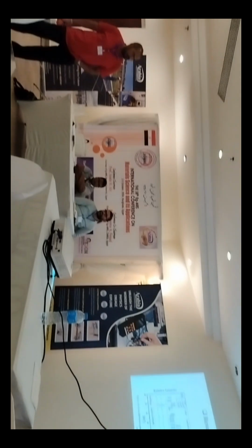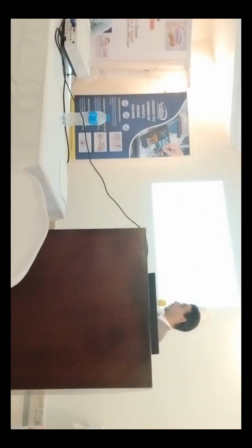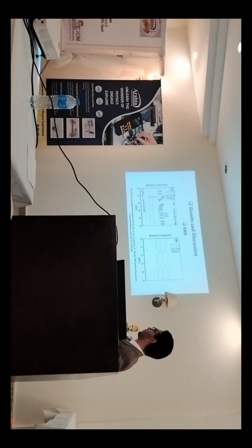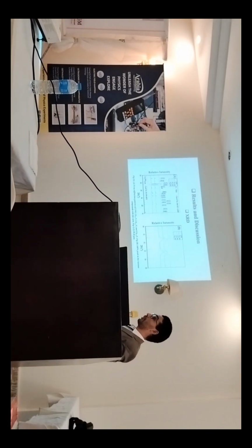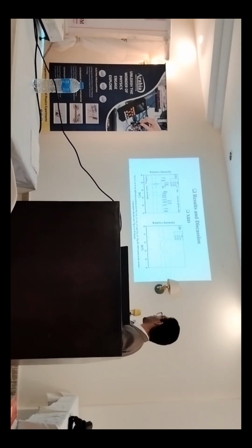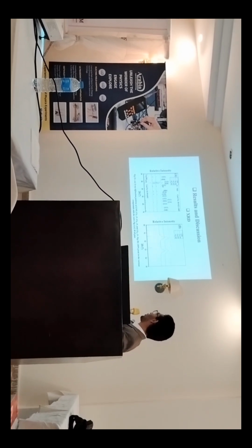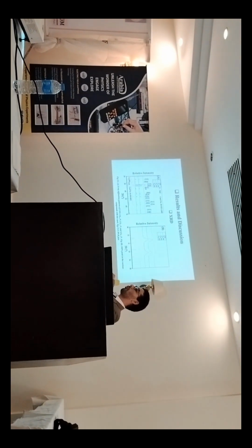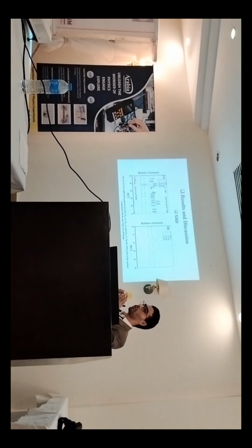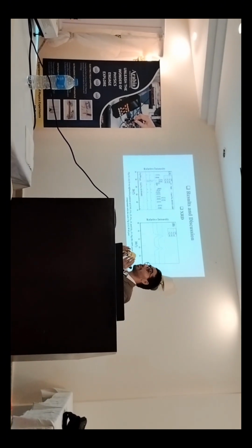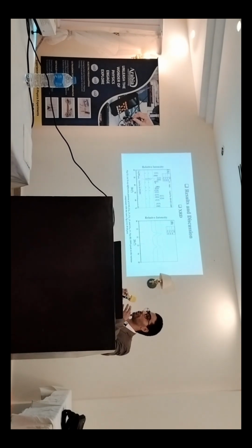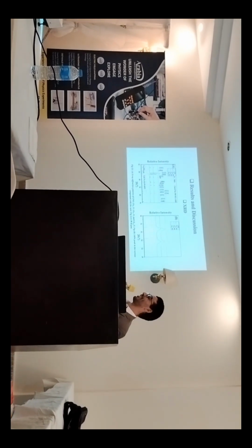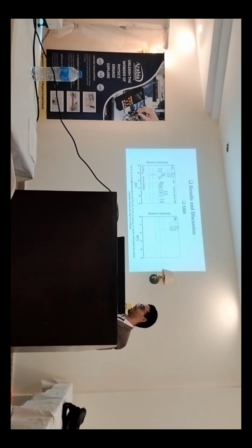Actually, this is the main lanthanum nickelate phase, and this is the doped samarium. So we have checked this peak, the main peak, which is 100%. We are actually confirming the phase over this. So there was some broadening and some shifting. This is related to the new ion we have added or doped into our sample. It may be smaller, so it will cause some shrinkage in the lattice unit cell, or if it was larger, it will expand. So that's why the spacing and all these peaks change.